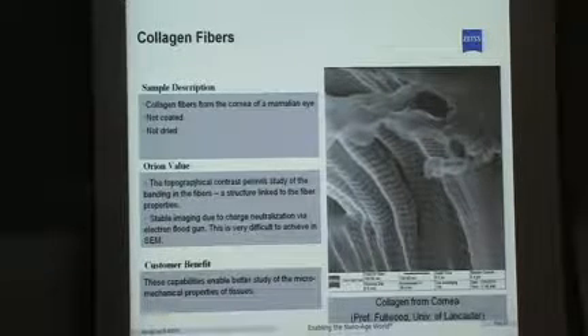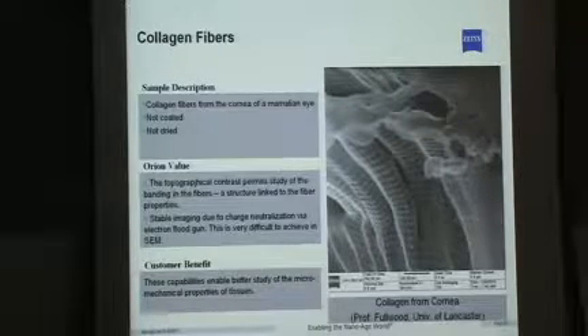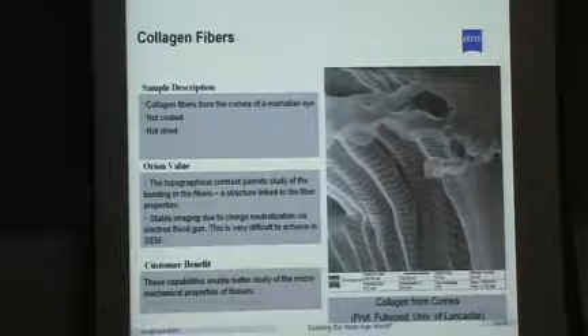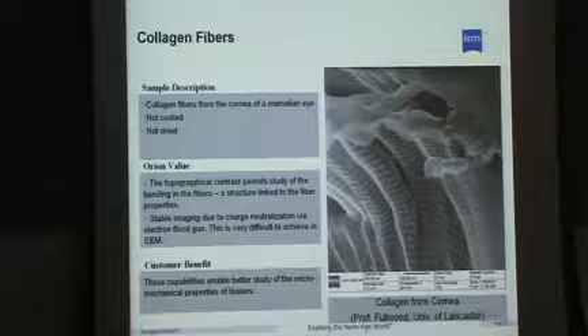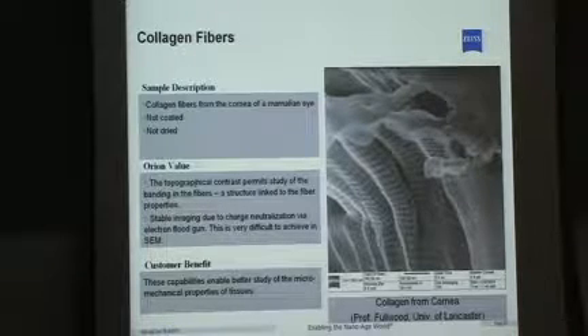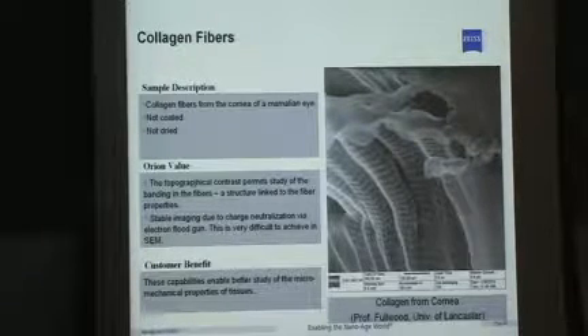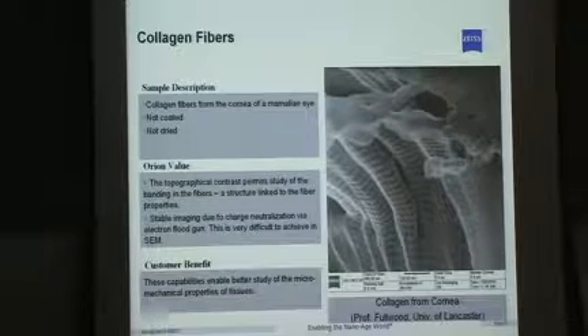These ringed bands here are very hard to see, and the tissue also tends to charge very much. We were able to shoot these images without having to metal coat. We didn't have to hide the surface, and therefore we could see these bands quite clearly and know that they're not an artifact of the preparation.